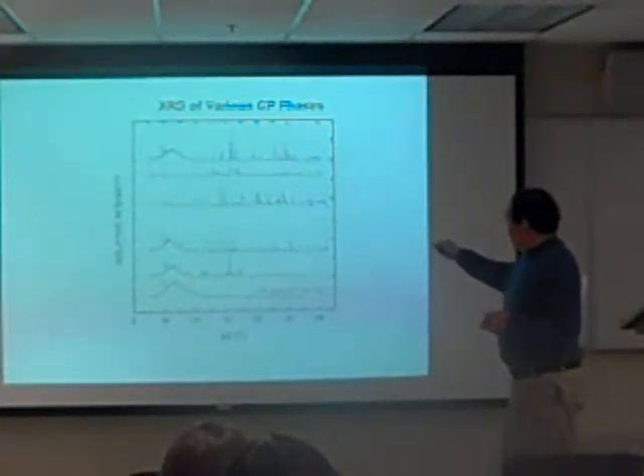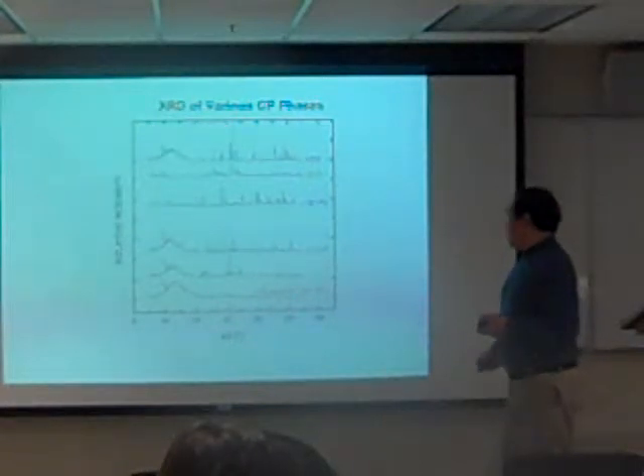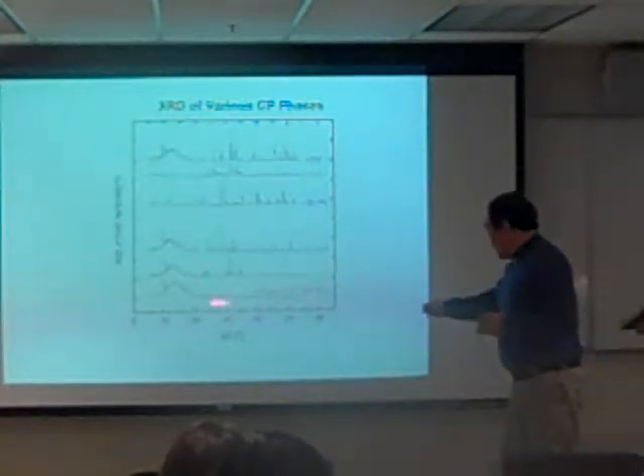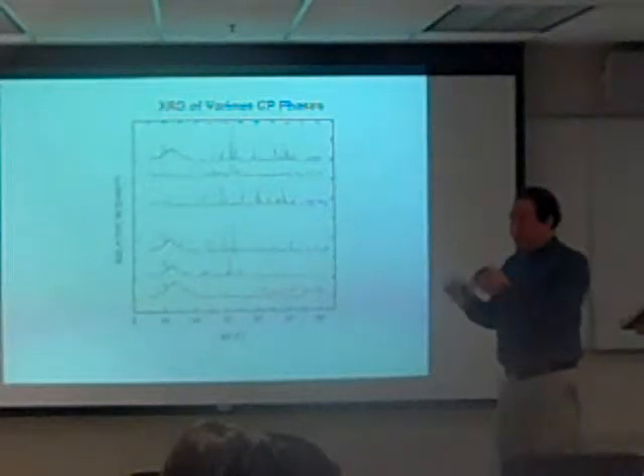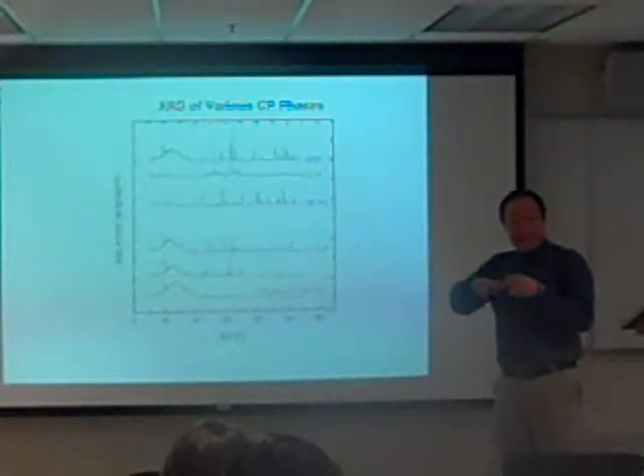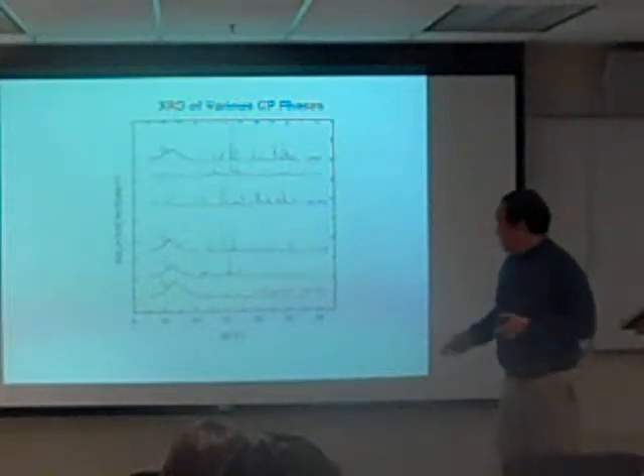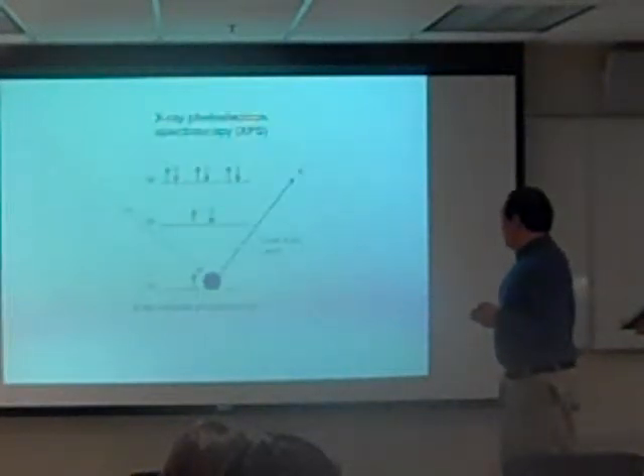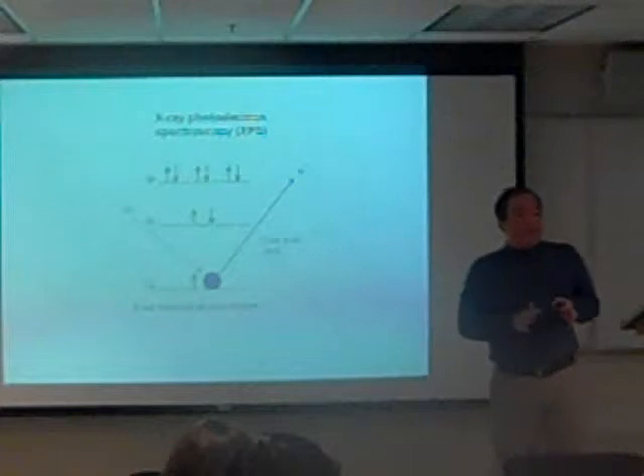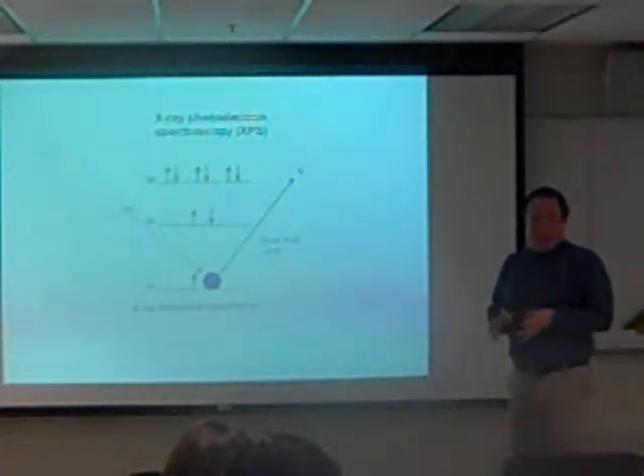Well, we just used a conventional XRD. You can see that there are no peaks. That's after we took the material and interacted it with the solution where we think the onset of nucleation and growth would occur. There's no signal there. So the way to do that is to do electron spectroscopy.